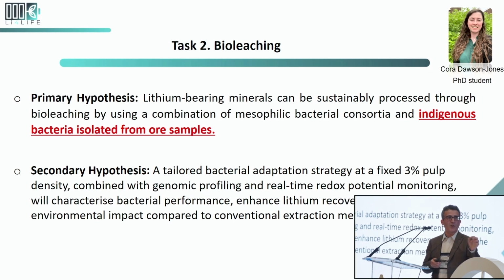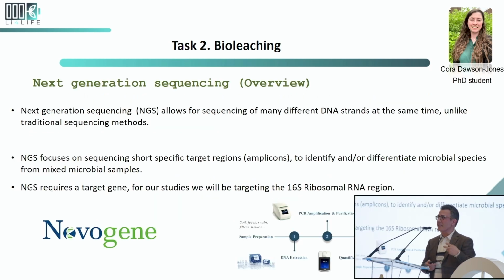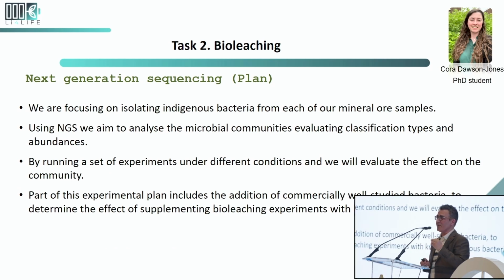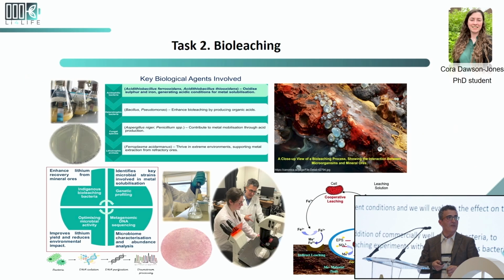In terms of the bioleaching, our idea is, since we collected different samples from different parts of Europe, we're trying to extract the indigenous bacteria from these samples, and we have a team jointly working with our life science group. The idea is whether there is any specific indigenous bacteria, based on the mineralogy, living in that component. So far, we have collected the DNA data, and we will sequence them and see. One thing we have noticed is that the composition of the metal is a dictating factor. If there's any poison metal in any component, then there is zero chance the bacteria grow. So that would be good, specifically for people trying to perform bioheap leaching or anything. Knowing the composition of the sample would be really great in order to improve the efficiency of the bioleaching.